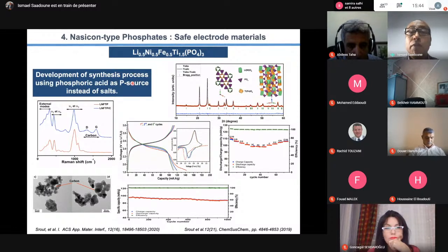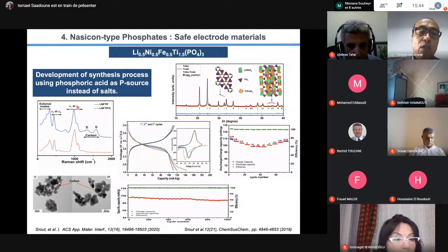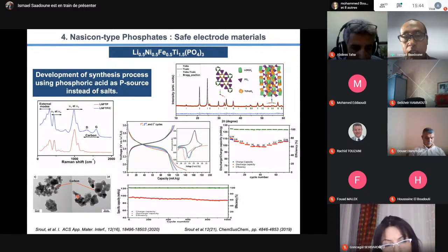So we developed a synthesis from phosphoric acid. It's very important because in the literature we prepare phosphate mainly from salt, but here we had the challenge to use phosphoric acid. This is a synthesis where we should control the pH - very important. So we succeeded in obtaining a NASICON-type structure with good structural refinement, and we checked the existence of carbon inside. Here is a comparison between the phosphate without coating and phosphate with coating, and we see that we have the existence of carbon. TEM shows that we have particles covered by carbon, which is what we need.